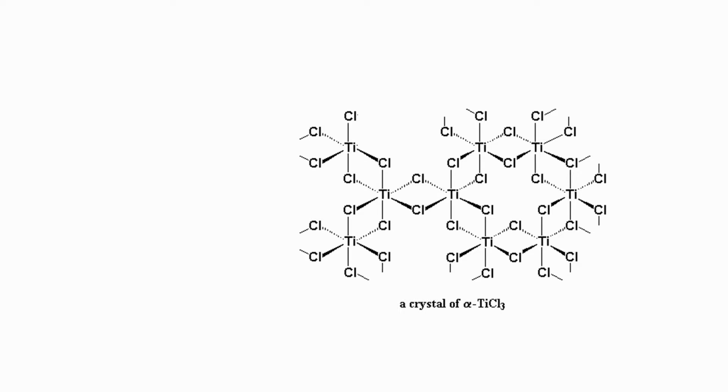The Ziegler-Natta catalyst, either TiCl3 or TiCl4, is used along with an aluminium-based catalyst in vinyl polymerization to make polymers of specific tacticity, such as unbranched polyethylene and isotactic polypropylene. Tacticity is a vital factor that influences the polymer's physical properties, such as rigidity, strength, melting point, and solubility in different solvents. Without this catalyst, we will need to utilize free radical vinyl polymerization, in which case we can only get branched polyethylene as some monomers will not be able to polymerize at all.